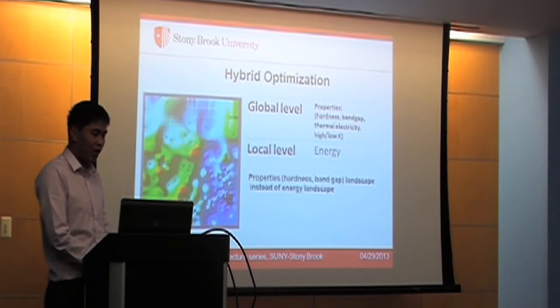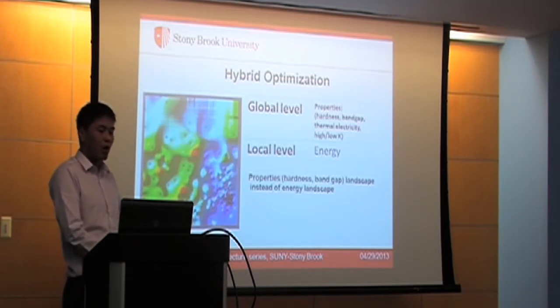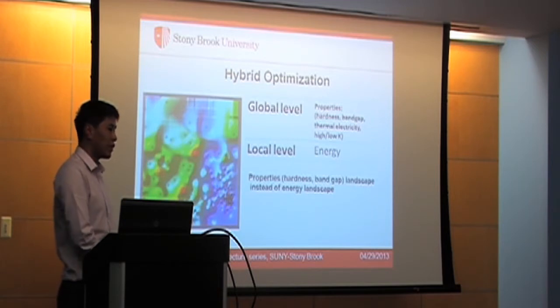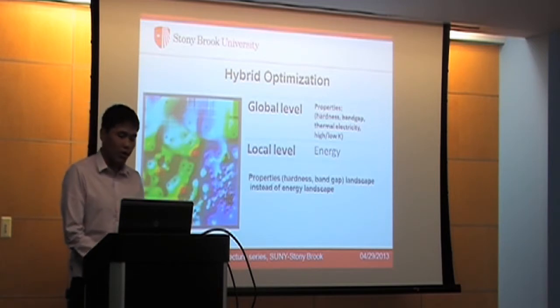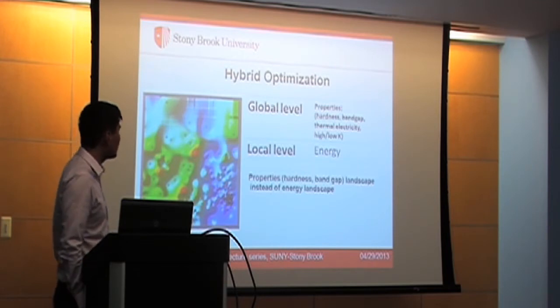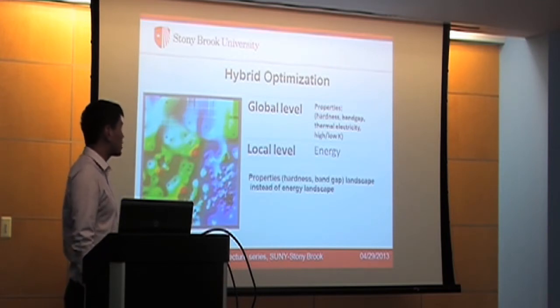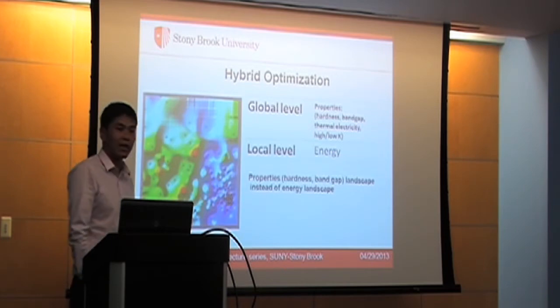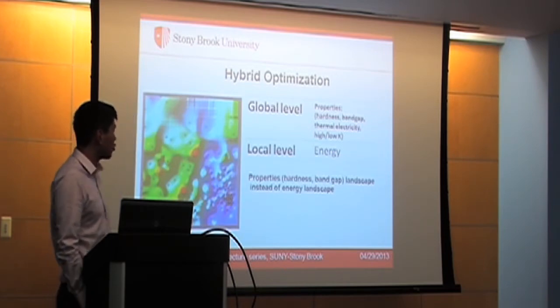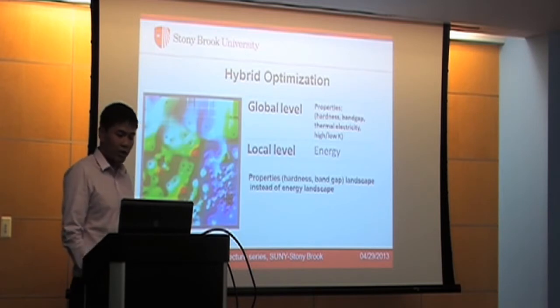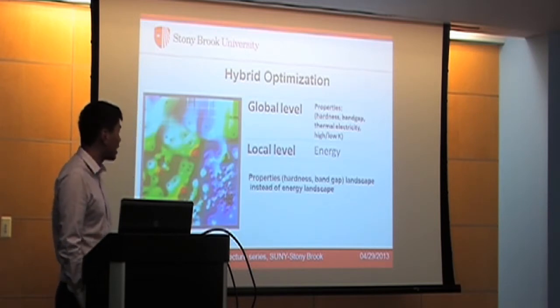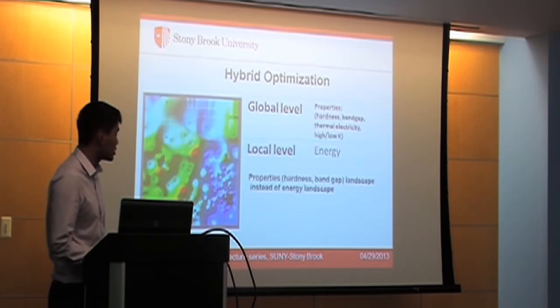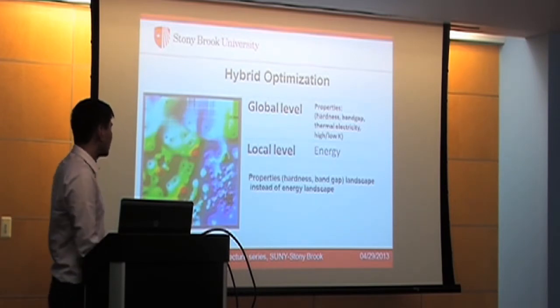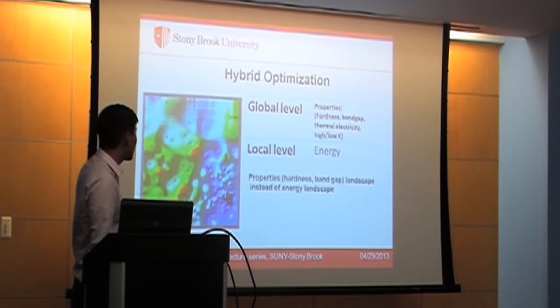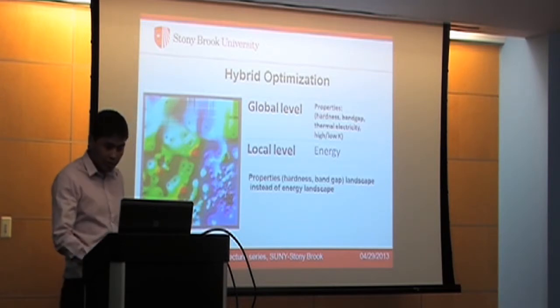So we developed a formula, so-called hybrid optimization, to search for materials with target properties. We split the searching into two levels. At the global level, we use the desired properties such as hardness, band gap, thermal conductivity as the criterion, while at the local level, we still use energy as the criterion to relax structures. So in this case, we are no longer exploring the energy landscape, but the landscape of the properties.